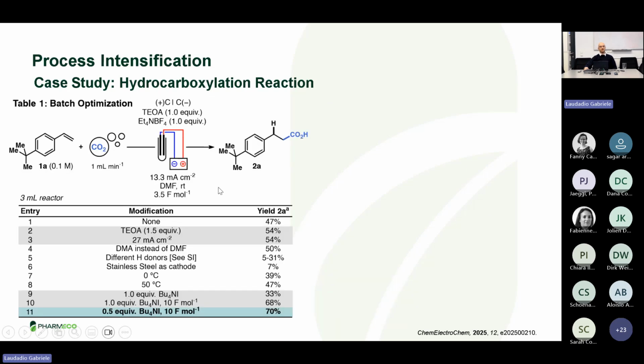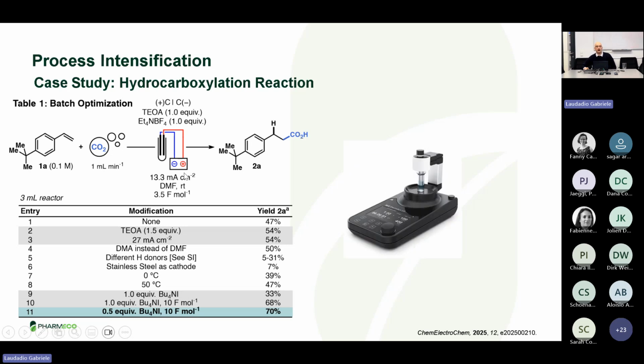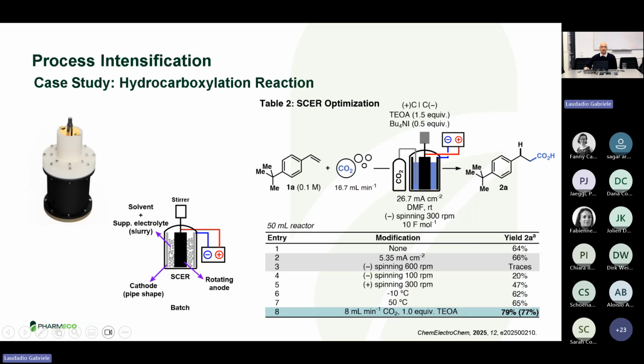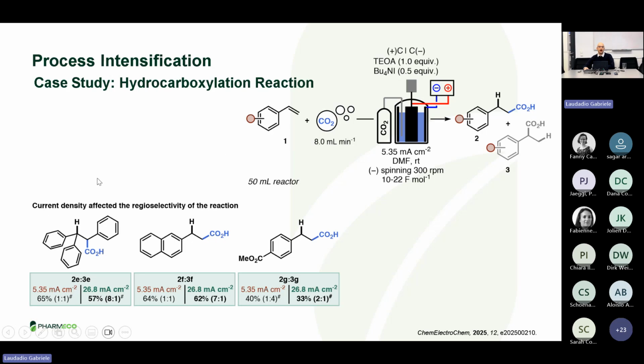Basically, we started by optimizing the reaction in the IKA ElectraSyn cell until we obtained around 70% yield. And then once we were satisfied with the batch optimization that was using a large excess of CO2, we moved to the spinning electrode reactor. And in this case, we managed to control the amount of CO2 in order to have a limited amount of equivalents and obtain the product with the higher yield at higher scale, because this is 50 milliliters compared to the 3 milliliters of the batch.